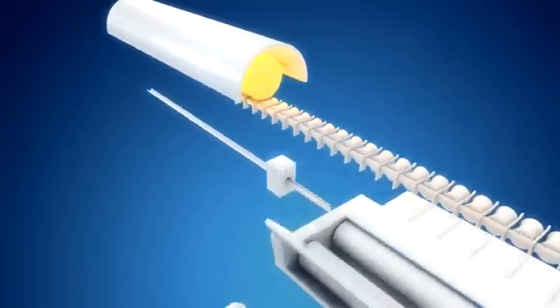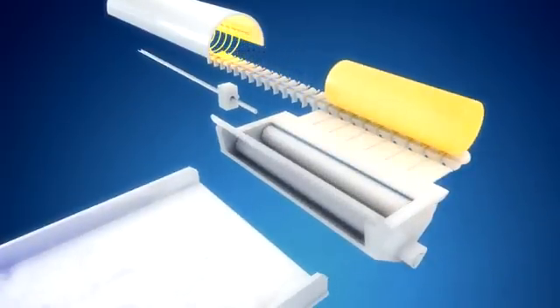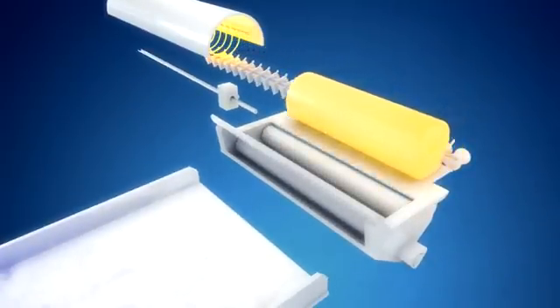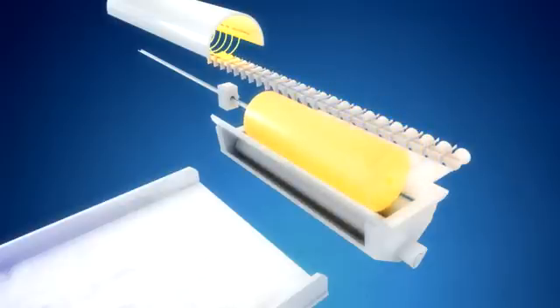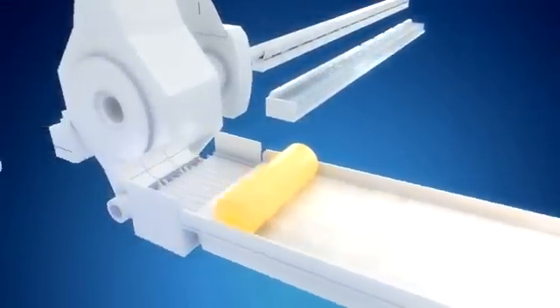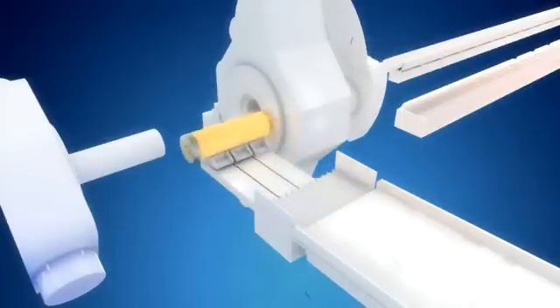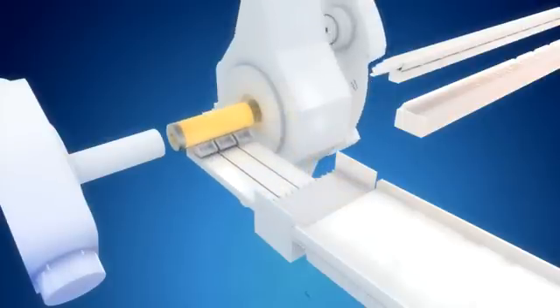The extrusion billet is heated to about 1200 degrees centigrade and then lubricated internally as well as externally with a glass powder. A mandrel is inserted into the hole in the billet.